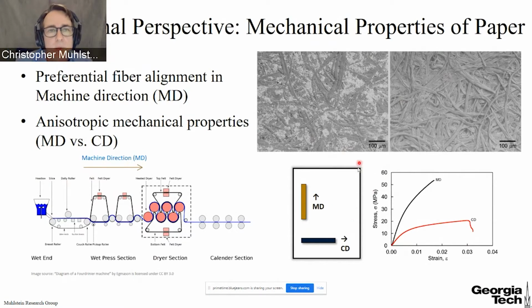And it turns out that when we look at the mechanical properties of paper, shown in the lower right-hand corner here, we have stress, which is the force divided by the cross-sectional area, or thickness of the paper times its width. And then strain is how much elongation, how much extension, we're seeing. You can see that the black curve has the machine direction. That paper goes up higher. It's stronger than in the cross direction. This general bias is a byproduct of the fibers being aligned more along the machine direction than the cross direction.